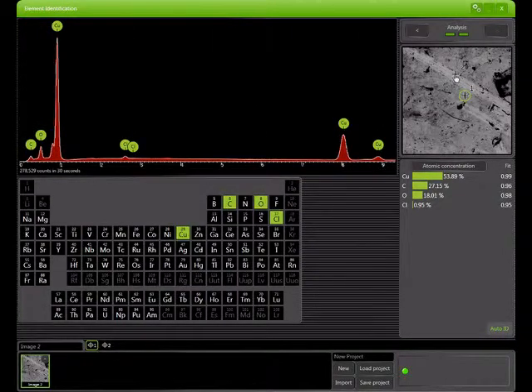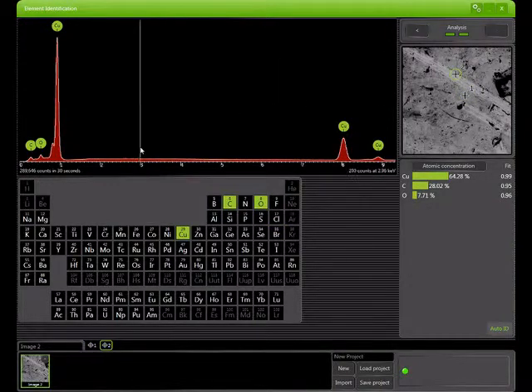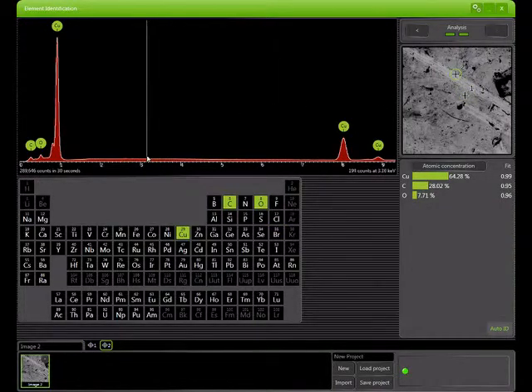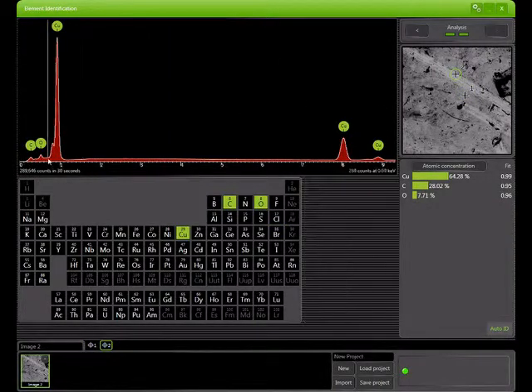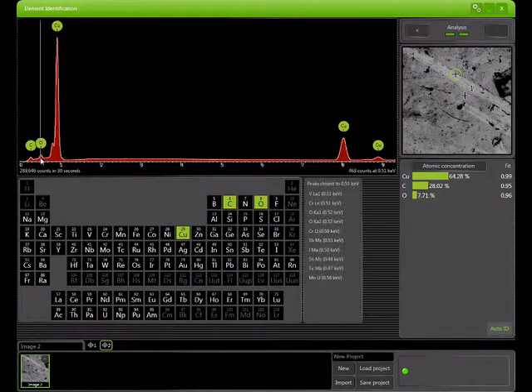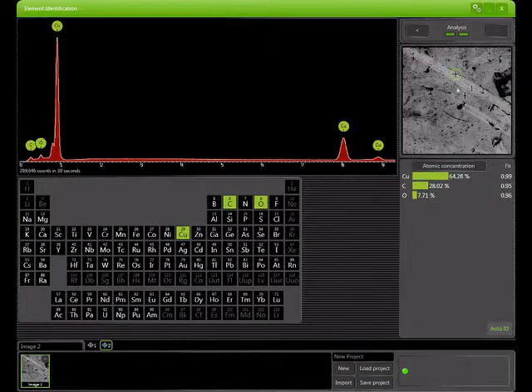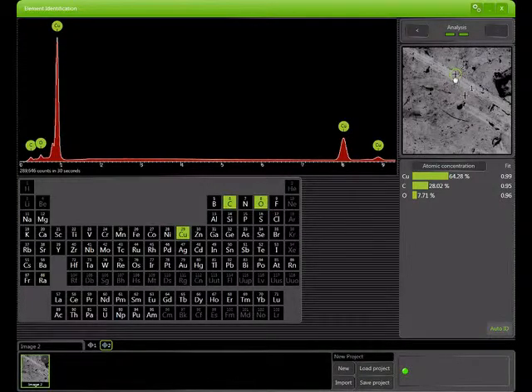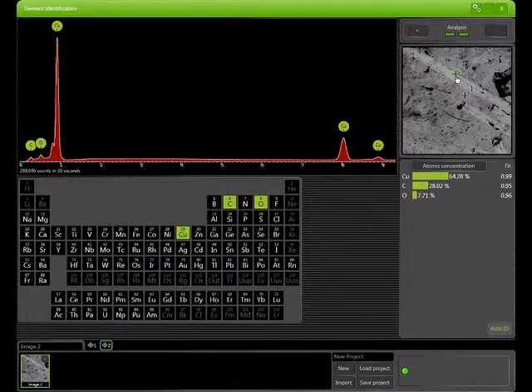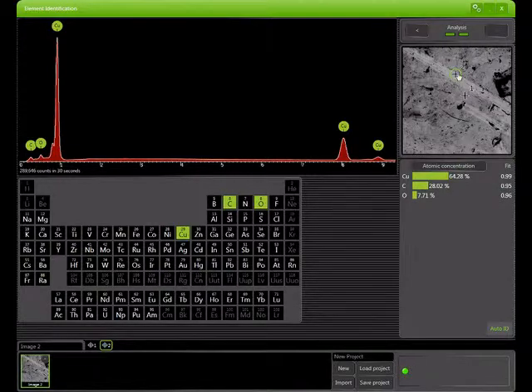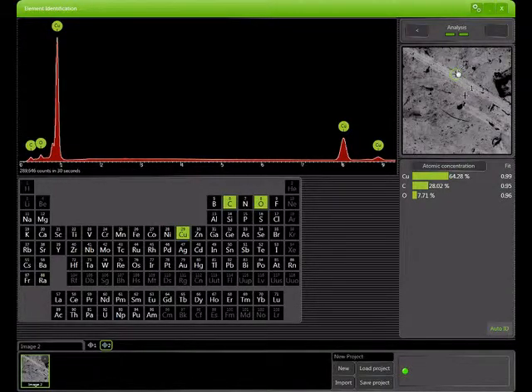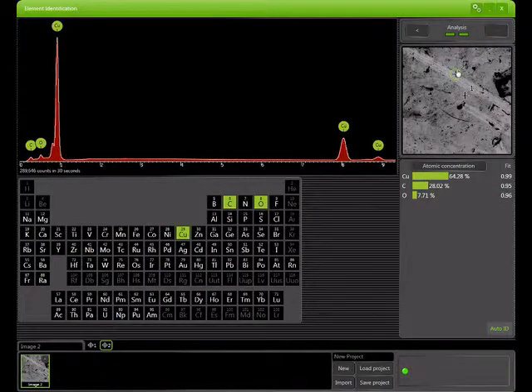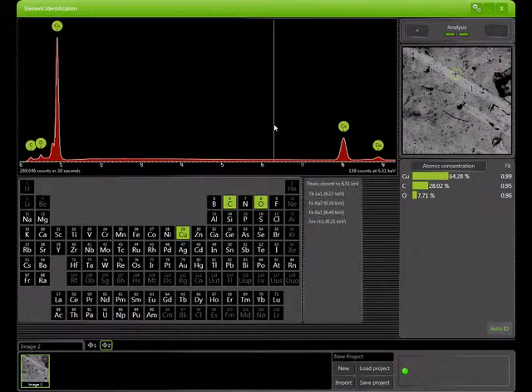If we look at the cleaned off area, point two, you'll notice that there's no chlorine peak and there's less oxygen present. We say the beam is trying to be in here. It doesn't have to do a perfect job of this. Some of the beams will be detecting outside of the area, and this was a quick cleaning job where I simply used a razor blade to clean off the surface.